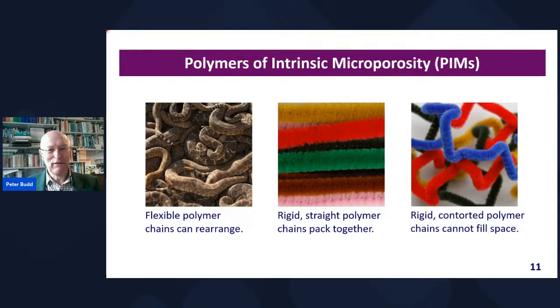And of course, we can make very rigid polymers that are quite, if you like, straight and stretched out, but they tend to stack together and be very difficult to dissolve or do anything with. But if we have this polymer backbone with a combination of features, the sites of contortion that make it twist and turn, but also the lack of conformational flexibility, then we end up with something which traps a lot of free volume. It traps a lot of space that other little molecules can get into. And that's the basic concept of a PIM.